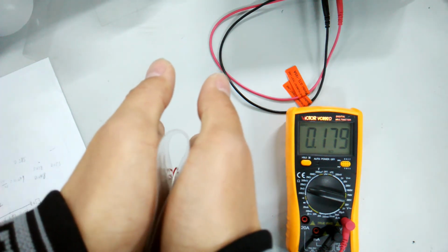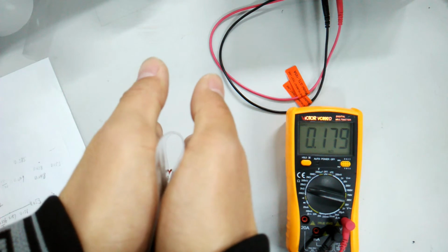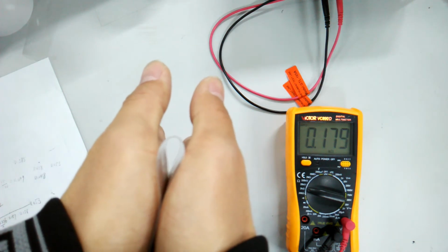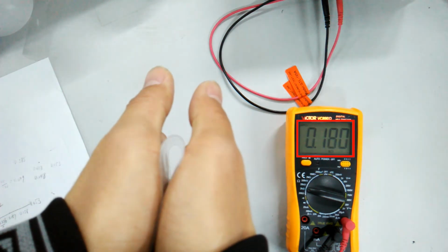When the bending reaches a certain level, the resistance starts to increase. We think that when the resistance reaches 180 ohm, the ITO film has reached the critical bending radius. At this point, the minimum distance between 2 points on the hole is measured 12.9 millimeters.